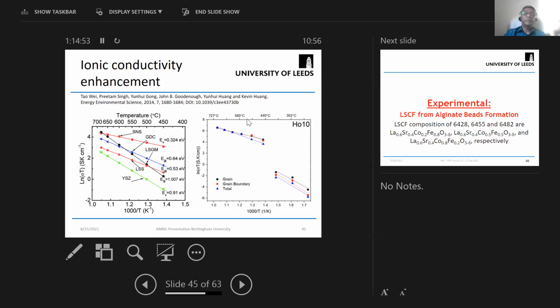This is our material, produced by the alginate method. And what you see here is that in our case, ln sigma T at a similar temperature, 727 degrees Celsius, is about 6.5. So you can see that our material produced using the alginate method has better properties, at least 2 orders of magnitude higher oxide ion conductivity compared to the best known material so far in the literature. So this is what we are exploring at the moment, why there is a difference of 2 orders of magnitude compared to some of the competitive materials.